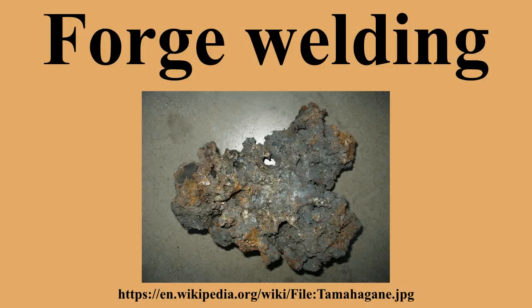Unlike other diffusion methods, in forge welding the metals are heated to a high temperature before forcing them together, usually resulting in greater plasticity at the weld surfaces. This generally makes forge welding more versatile than cold diffusion techniques, which are usually performed on soft metals like copper or aluminum. In forge welding, the entire welding areas are heated evenly. Forge welding can be used for a much wider range of harder metals and alloys, like steel and titanium.